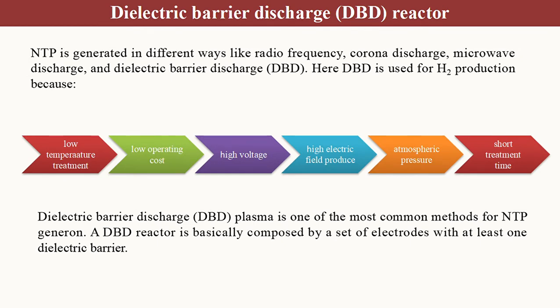Dielectric barrier discharge reactor. Dielectric barrier discharge plasma is one of the most common methods of non-thermal plasma generation. A DBD reactor is composed of a set of electrodes with at least one dielectric barrier between them. Due to the presence of the dielectric barrier, higher voltages are required for DBD to generate a high electric field between the electrodes that is necessary for plasma formation and causing breakdown in the gas. Non-thermal plasma can also be generated in several ways, including electrical corona discharges, radio frequency discharges, and microwave discharges. But the advantage of DBD over others is that it produces a homogeneous discharge with lower energy consumption, resulting in no spark formation inside the streamer channel and no overheating. Additional advantages of DBD reactors are their scalability, effectiveness, and low operational cost.